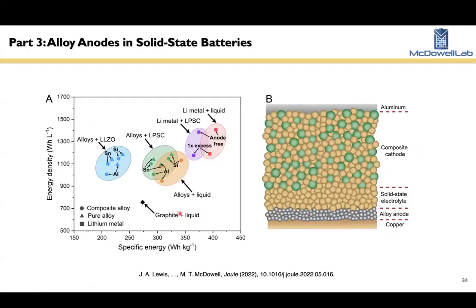So alloy anodes, examples are silicon, tin, aluminum. These are materials that alloy with large amounts of lithium to form new phases, and they have high specific capacity. Silicon has been investigated, of course, for many, many years for lithium-ion batteries. There are commercial lithium-ion batteries that have silicon with liquid electrolytes. Usually there are very complicated particulate structures that are necessary to minimize SEI formation in liquid electrolytes with these materials. But this is continuing to be commercialized and improved for commercial cells.